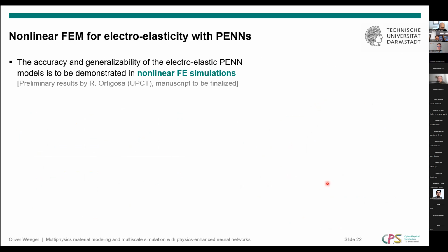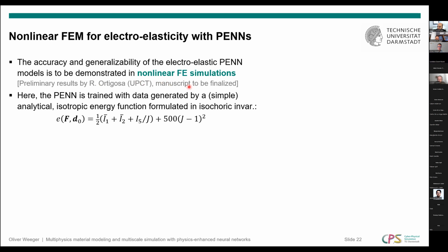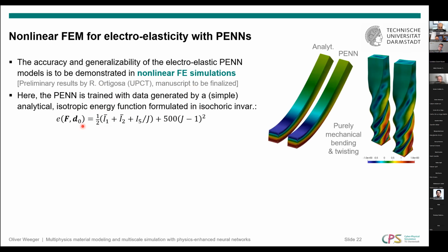Now, finally, we are currently in the process of implementing this into nonlinear finite element simulations, where our collaborator from Cartagena, Rogelio Ortigosa, already has some results, but we haven't submitted a manuscript about this yet. So for what I'm going to show next, we just use a simple isotropic strain energy function with isochoric invariants to generate data. We fit the neural network model to this data, and then we implement this in a finite element simulation and compare the finite element simulation with the analytical model versus the finite element simulation with the neural network-based model. So here you see 2 cases where we have purely mechanical behavior.